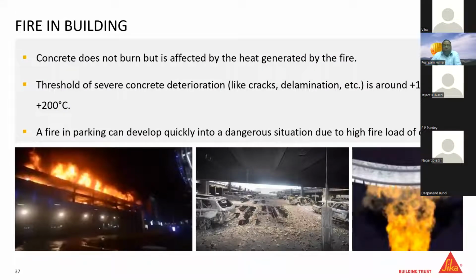So what happens when a fire happens? The concrete does not burn, but when the temperature increases to 150 or 200 degrees centigrade, the concrete starts getting cracks or delaminating. Because of the continuous fire, it will completely damage. When the temperature goes to 400 degrees and above, the concrete will completely crack and delaminate. This will come to a collapse situation.